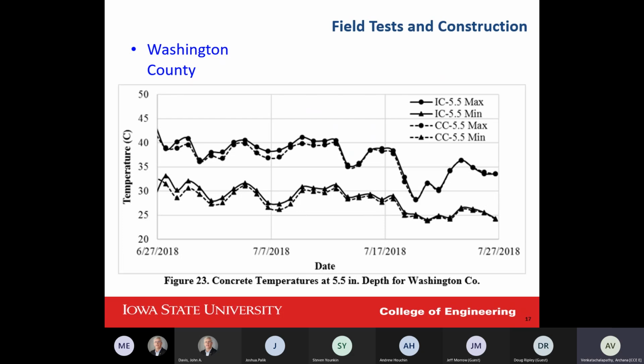In the beginning, for two slabs in the same location, one is internal curing and one is normal concrete. The temperature in internal curing is higher than in the normal concrete. I mean, these two, for example. So we see more difference here than here, which means the hydration here is higher, and after a month we are facing kind of the same hydration, which means the hydration is going on in the first month, which is the most important part of the concrete, up to the age of 28 days.